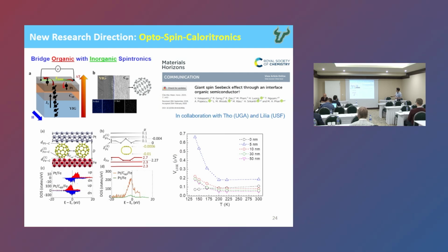So this shows that it's possible to enhance spin-Seebeck or spin charge conversion by introducing a very thin layer of semiconducting materials. And C60 is a very interesting material because when you form the interface, it tends to change the surface of the material as well. In this case, what we detect is that C60 reduces the surface magnetic anisotropy of yttrium iron garnet, and that enhances the effect as well. So eventually, C60 not only reduces the conductivity mismatch, it also enhances spin mixing conductance, and that enhances the overall spin charge conversion. With this one, we are limited to just 5 nanometer thickness.